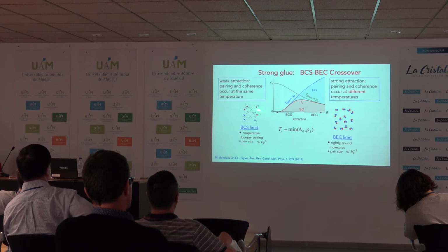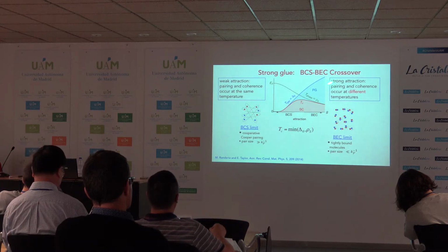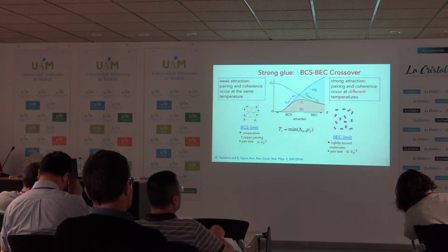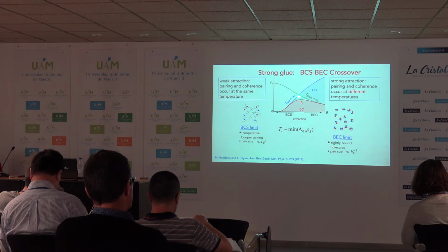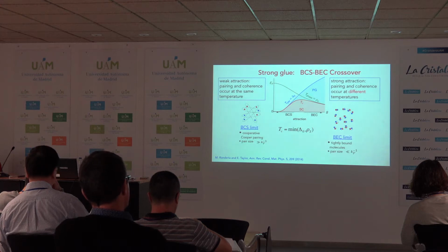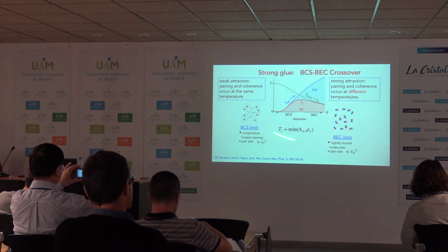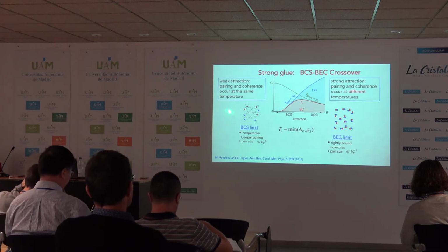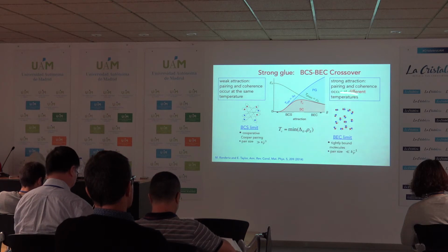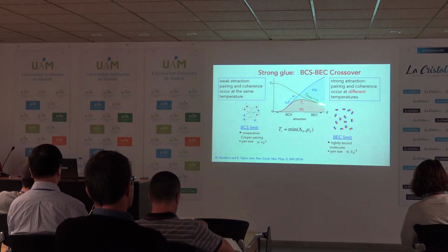Okay, now going beyond that, let's say you start increasing the glue, which is this attraction, let's say, that's G. What happens is the pairing scale will start to go up and increase with the glue. So the greater the attraction, the harder it is to break pairs. However, the superfluid stiffness is either constant or decreases with G, and at some point these two energy scales cross. That part is important because Tc, the transition temperature, is governed by the lower of these two energy scales. So at small attraction, it's really the pairing which is describing your transition, and that's the BCS paradigm. But at large coupling, since now ρS has become the smaller scale, that governs the transition.